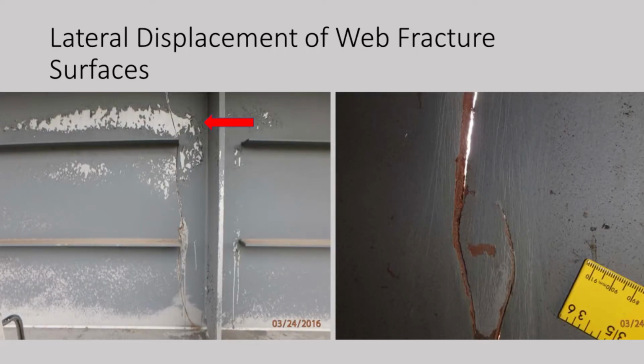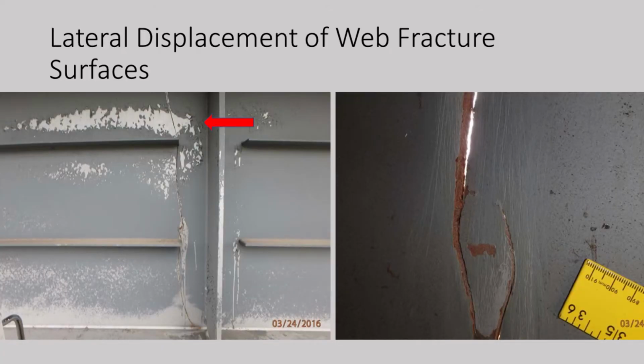The first thing is to look at this paint that popped off around this upper stiffener right there. That indicates there was fairly high strain, distortion in that area that caused that paint to come off. And we see a little bit in this area here as well. Then we look at this picture, and we've got lateral distortion in the fracture, in the web. That takes a lot of energy, a lot of stress to cause that. It probably didn't distort like that until the fracture occurred, but there it is. So it looks like a lot of stress has been put on this bridge. But what we saw firsthand didn't seem to support anything like that.